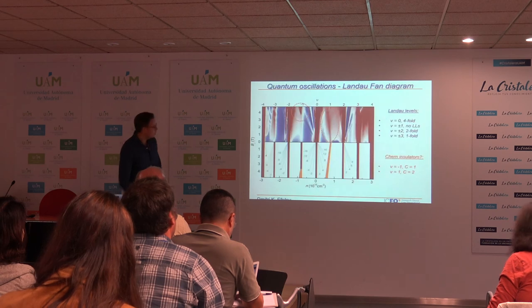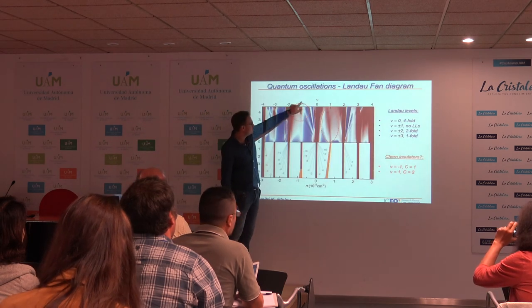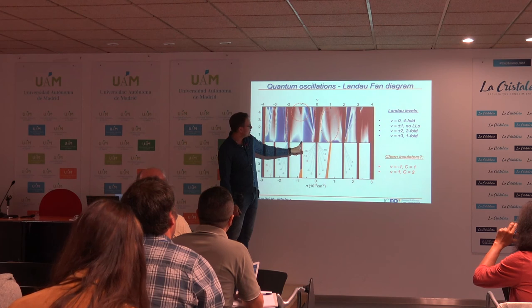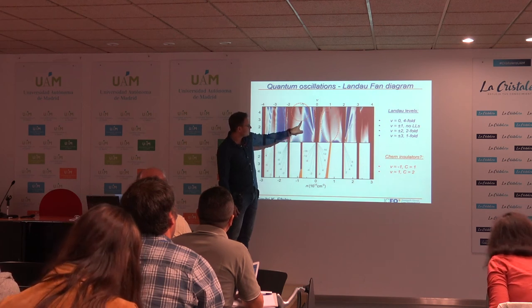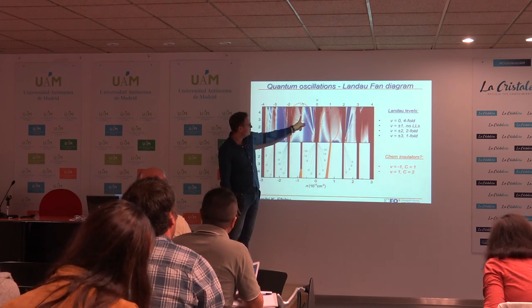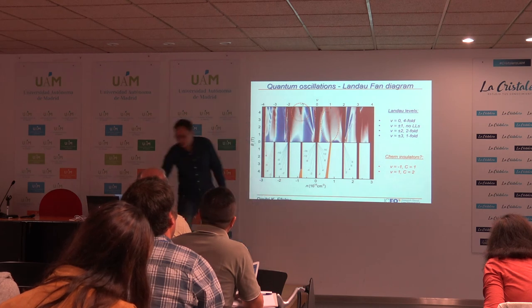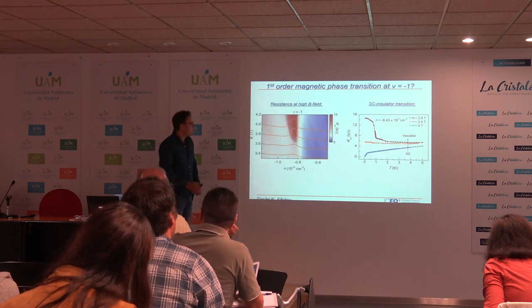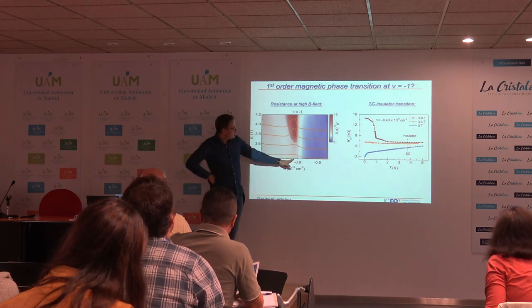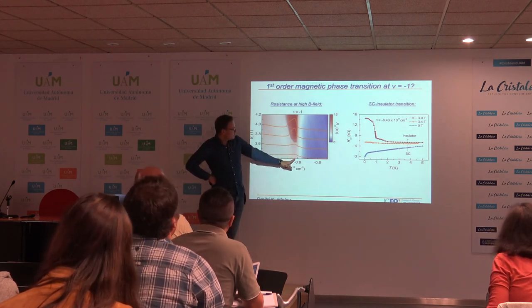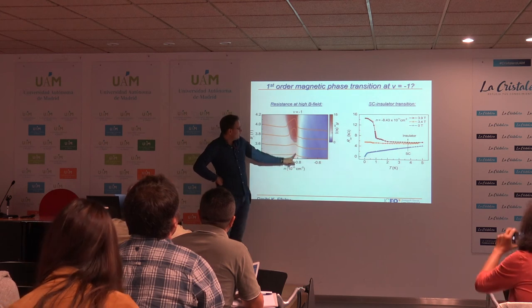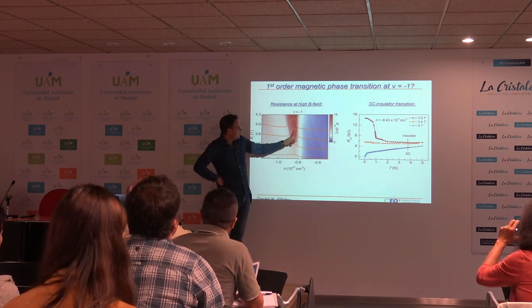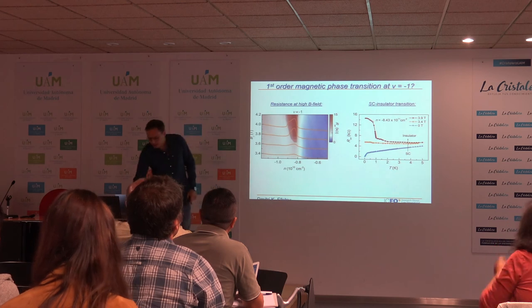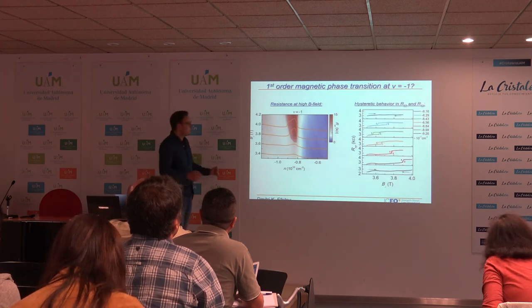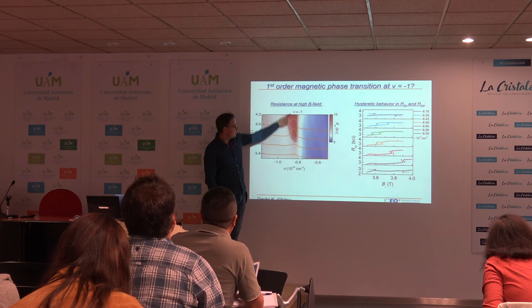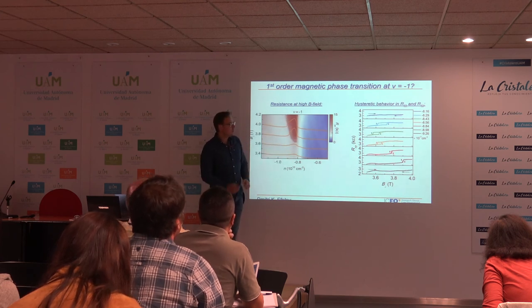Interestingly, if we zoom into this region here, where we first have a linearly developing insulating state in magnetic field, and then it gets this slope shape, we first observe a metal to insulator, superconductor to insulator transition. We hit this state, and the system becomes much more insulating. And second, which is much more important, if we go with magnetic field along this line, we also observe magnetic hysteresis.